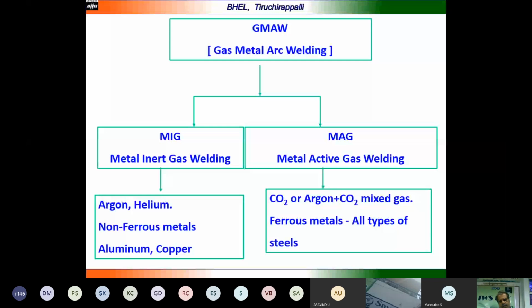How much percentage of argon and CO2 can we use? For conventional structural welding, we can use 80 to 20%: 80% argon, 20% CO2. When it is going to pressure parts, made as per ASME or other codes, and it is going to work in a high pressure and high temperature environment, then it is better to go for 90 or 95. That is the way we have to work, and we have to increase that. So increasing the argon is for pressure applications, and for structural application we can have 80% argon, 20% CO2.